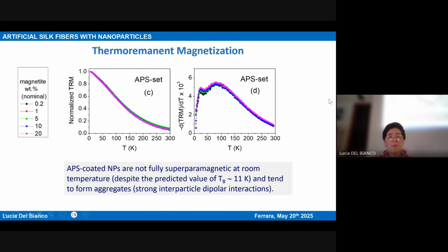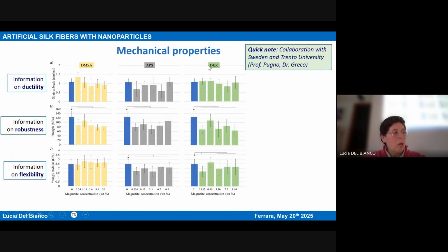Of course, for this type of system, the mechanical properties are very important, and therefore our collaborator measured the mechanical properties by performing tensile tests. And I have no time to enter into the detail. However, we measured different parameters. The strain at break gives information on the ductility of the fiber, the strength gives information on the robustness of the fiber, and the Young modulus gives information on the flexibility.